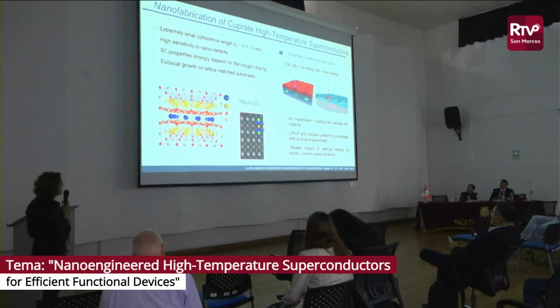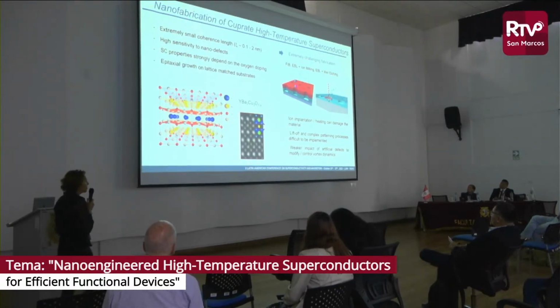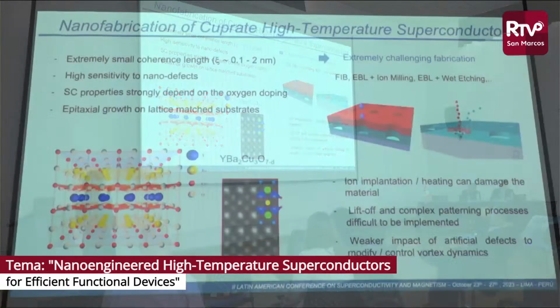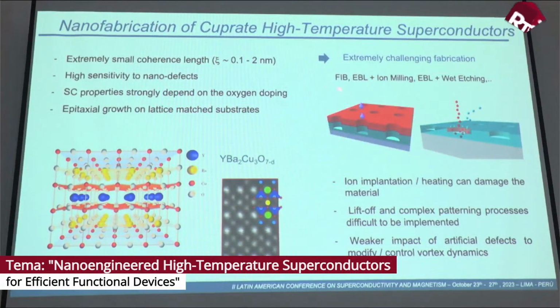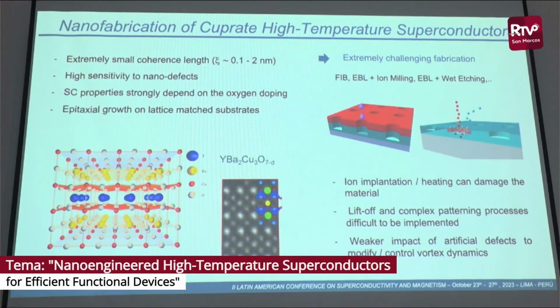Among the different approaches that one can use to fabricate nanoscale or microscale devices with high TC, we have different techniques: focused ion beam, electron beam, or a combination of different high resolution lithography techniques that can be used to nanostructure the system and fabricate the devices. But in all the cases, we need to be very careful because we can damage the sample during the lithography processes.